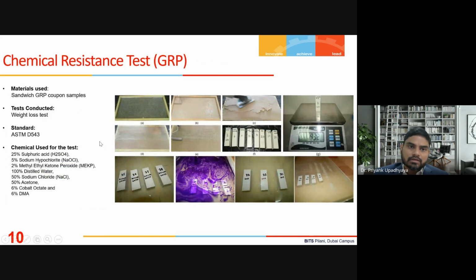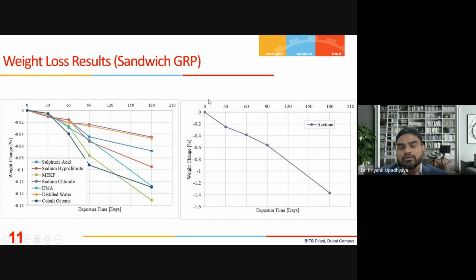The last sample that we tested combined all the layers in this GRP sandwich structure. After using the same hand layup process for all these layers, we prepared these specimens, weighed them before the test, and then measured the weight of the samples after 30, 60, 90, and 180 days. The same chemicals and the same standard were used. Looking at the data here, the most damaging chemical we have noticed is acetone, for which the overall weight loss is about 1.5%. For all other chemicals, the weight loss is very insignificant compared to this, roughly an order of magnitude of difference between these two.